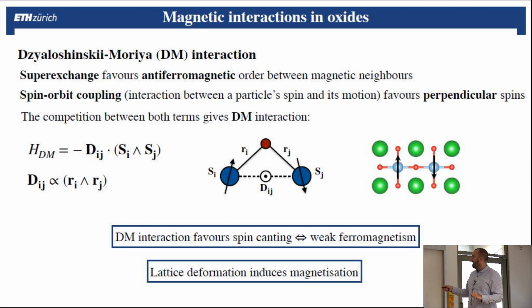So imagine that you have, that's what we had before. Now we are breaking a symmetry, and we don't have a 180 degrees bond here, but we have an angle between the bonds. So the Dzyaloshinskii-Moriya interaction can be defined by the cross product between the two spins, the spin here and the spin here, with the scalar product with this vector that breaks the symmetry. And this vector is actually the vector of the bond here and here. And it's also the vector product. So when you take that together, to minimize this, it will favor having this canting, meaning it doesn't stay perfectly parallel, but there is a small angle between the spins due to the symmetry broken here.